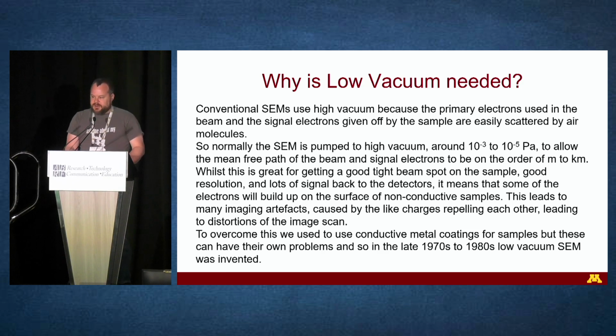So, yes, why do we need low vacuum mode? Well, conventional SEMs, as I said, work in high vacuum, and when you're shooting electrons at a non-conductive sample in high vacuum, many of them get stuck on the surface of the material, and then as you keep trying to shoot more and more electrons at them, they build up, and eventually they distort the scan line of the image, and so we get image distortions. And typically this was got around by putting a heavy metal coating on the material. Most people started using gold. People have moved to things like platinum and iridium and even osmium, trying to get finer and finer grain sizes, because what you don't want is for your coating to have some feature that you can image that you then mistake as part of your material.